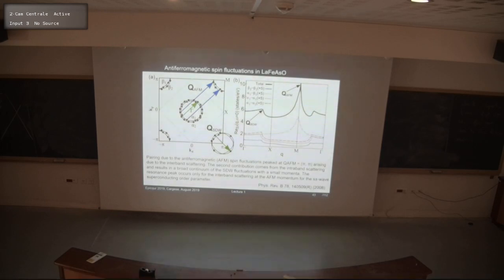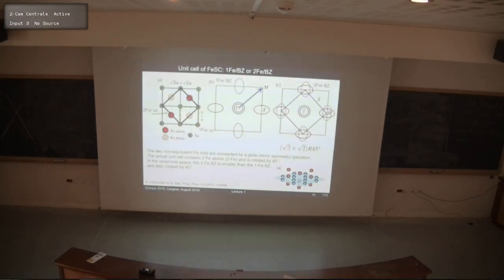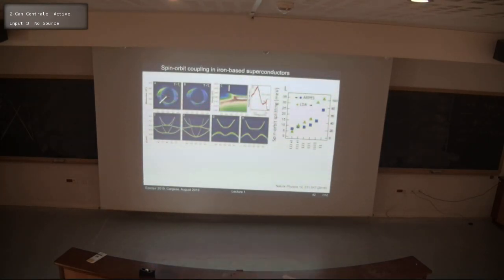Question? Yeah. In the previous slide, which of these are experimental data and which of these are simulations? So these are experimental data, and I think these are simulations. These are ARPES data focused only on the electron pocket, and this is a cut through the dispersion away from the Fermi level. If you would go through the middle of this plot, you will get different intensity where the different bands are, and the fact that you have separation is telling that the spin orbit is active there.